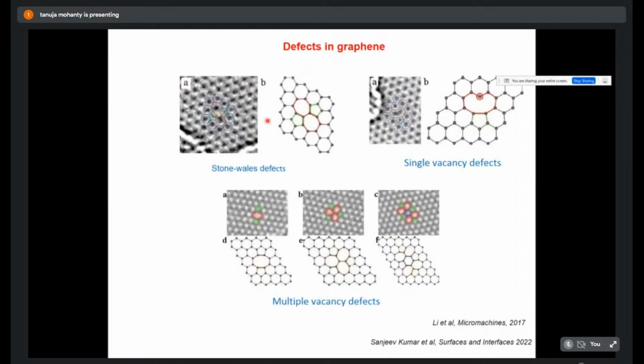So now I'll come to defects in graphene. One is the Stone-Wales defect. They're hexagonal, but you see that somewhere it is 7, and somewhere it is just 5, but it should be hexagonal, 6 bonds, and rather than that, somewhere it is changed to the Stone-Wales defect here. And you can have a single vacancy defect like that in the case of graphene. Also, you can have multiple vacancy defects. This graph is from the literature, and one of these is also a contribution in one of my students' work, which is written here.